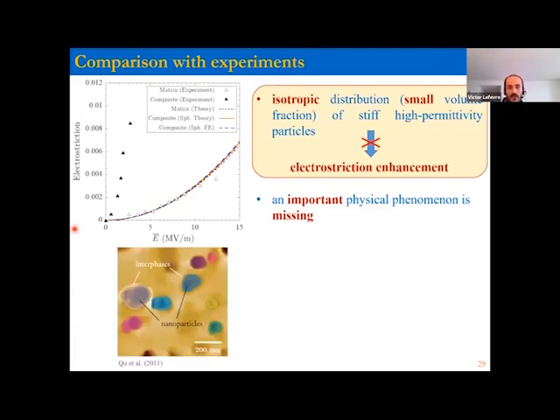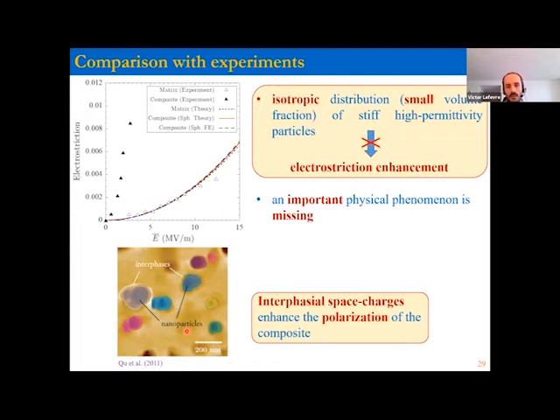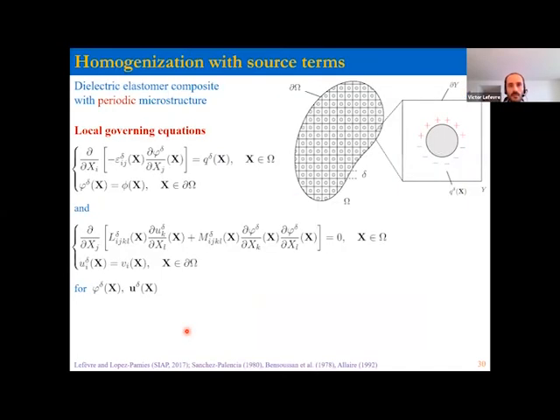In particular, we believe that we're missing interfacial phenomena. It's well known that for nanocomposites, you have these interfaces, regions at the boundary between the particles and the elastomer, where the behavior of the elastomer can be very different from what it is away from the particle. So here in particular, we believe that we're missing the presence of interfacial space charges that would enhance locally the polarization of the composite, and in turn enhance their electrostrictive properties.